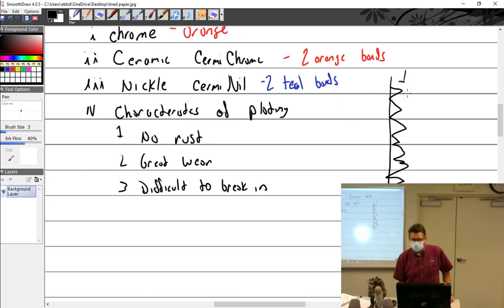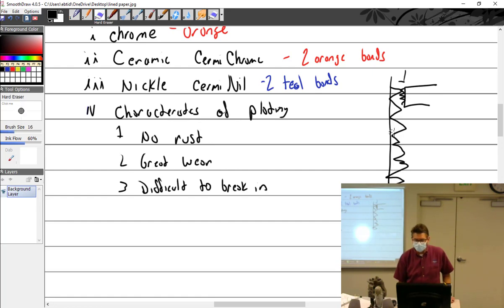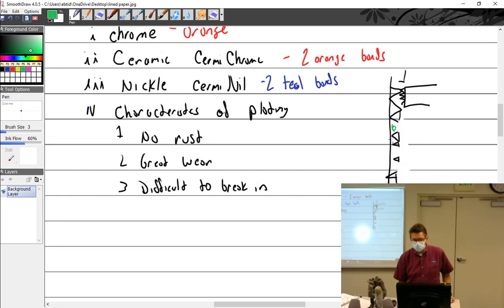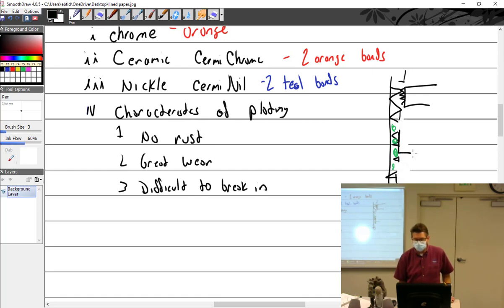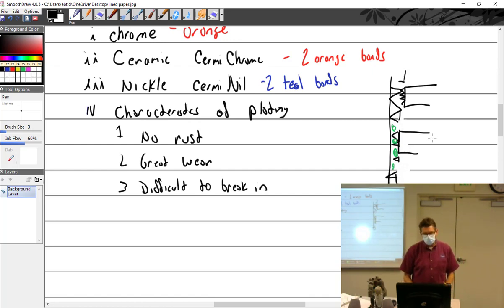You have your rings that are going across it and rings also have little ridges built into them. You don't want all of these ridges, you want it to wear in. When you wear in a cylinder, what you're doing is you're knocking down these ridges so that they're more flat. You still have the ability for oil to be held in these open areas.